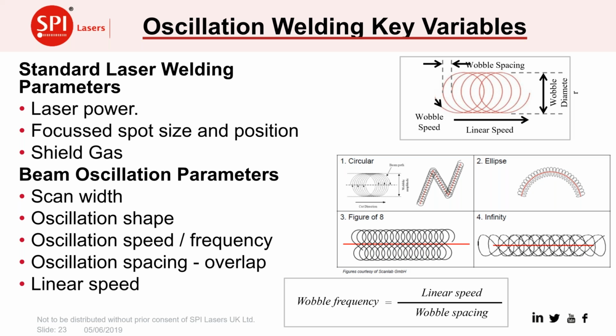But now we have the oscillation parameters: the width or the diameter of the oscillation, the shape of the oscillation, and the little table there shows that the standard ones are being used. And then the frequency at which we run the oscillations and the amount of overlap between the oscillations, which is governed by the linear speed. The frequency, the speed, and the wobble spacing are linked together by the little equation there. So there's quite a lot of choice.